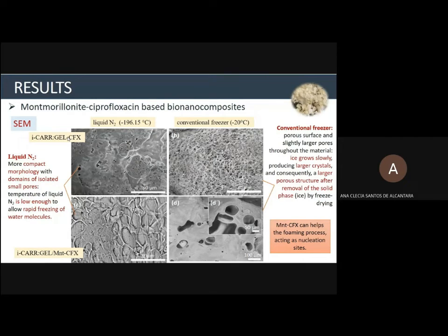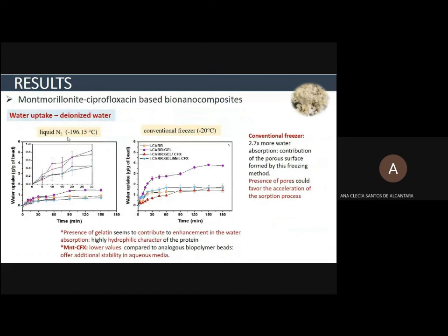This effect is usually observed in nanocomposite materials, where the porous structure resulting from the elimination of the ice crystals is more evident in materials prepared by conventional freezing than in those prepared with liquid nitrogen. In addition, in the case of the bionanocomposite materials based on montmorillonite-ciprofloxacin, the incorporation of the intercalation compound in the biopolymer matrix may help the foaming process, acting as nucleating agents, at the same time that it can modify the mechanical and physical properties of the final material.